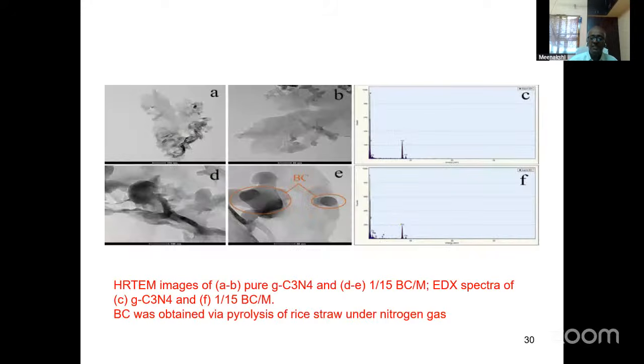So this is another biochar. Graphitic carbon nitride, g-C3N4, is one of the very good materials. This is graphitic carbon nitride with biochar obtained from rice straw, BC the biochar, and M is melamine, since g-C3N4 is obtained from melamine. They gave the ratio 1/15, that is one part of biochar and 15 parts of melamine, which is found to be more efficient. These are HRTEM images of pure g-C3N4, A to B, and D and E are for the 1/15 biochar. And here this is the EDAX spectrum.